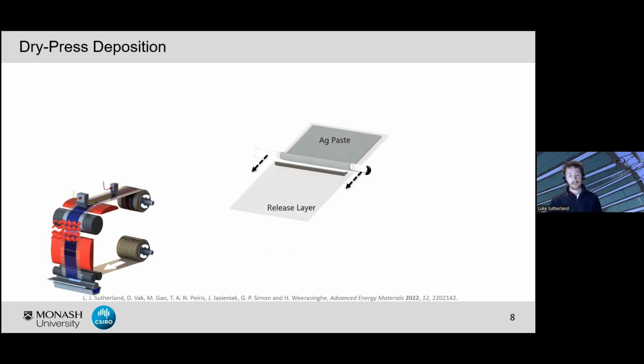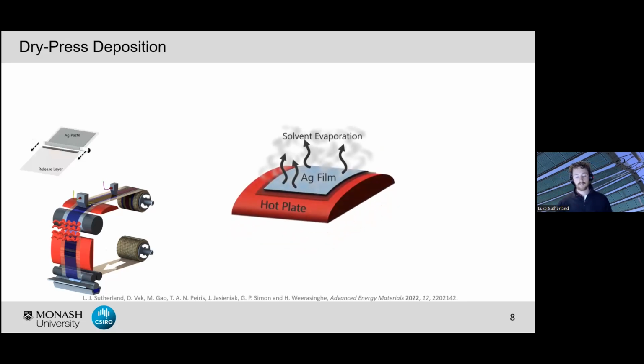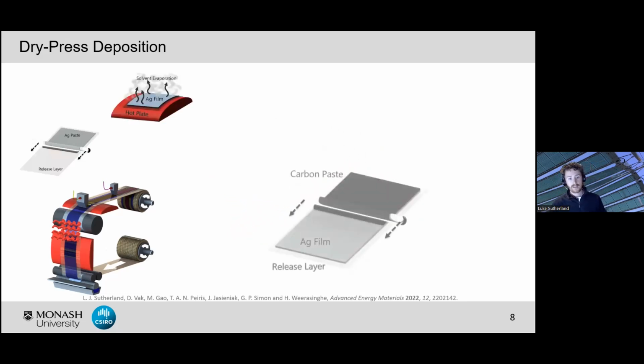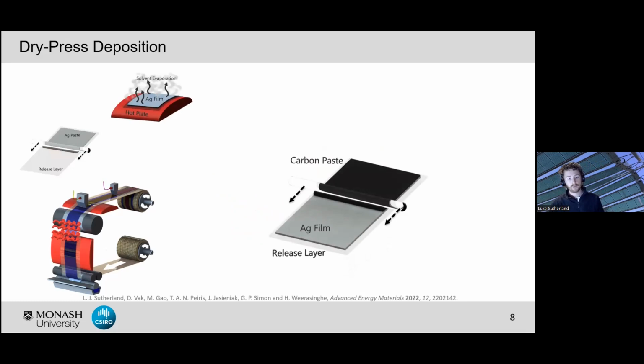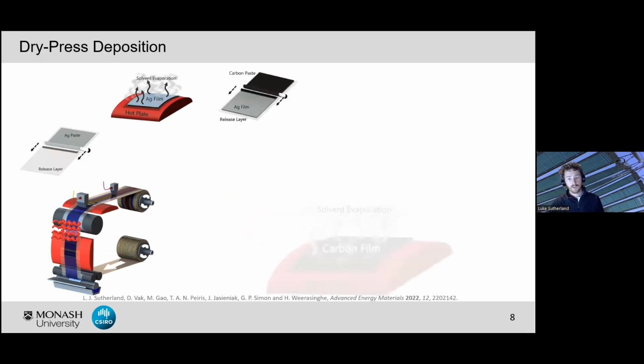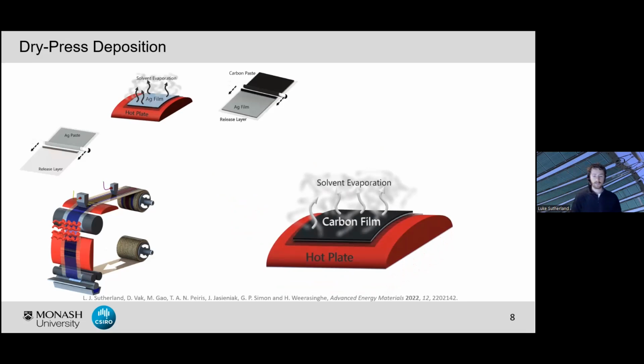This can be done using bar coating, as we can see on screen, but it can also be done using screen printing and also slot die coating. We coat the silver paste. We then pass this over a hot plate drying stage, and then similarly coat a carbon paste on top of our annealed silver film before finally passing this over one last hot plate drying stage in order to evaporate any of those harmful solvents that could potentially leach in and degrade our underlying device.